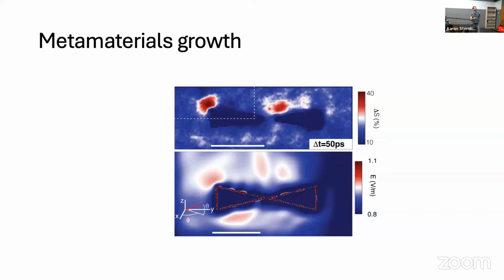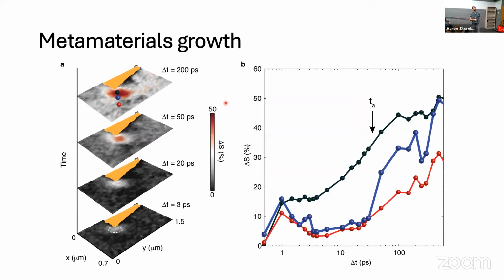You can see this in the patterns of the near field amplitude, which agree fairly well with finite element simulations of the local electric field. And this allows us to monitor the growth of metal that we anchored to a specific site in real space as it grows out into the rest of the film. So how do we know this is actually happening? Well, there are two key pieces of evidence if you look carefully at this data.